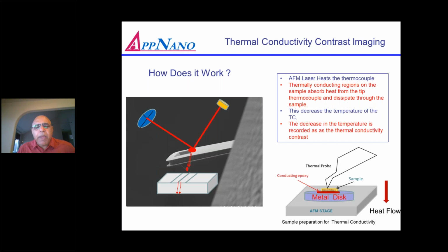The important part is to make a sample, and this is very, very critical. Sometimes if you have a polymer, you have a tendency to stick the polymer on a metal disc, and the metal disc is glued with a sticky tape on a stage. That's a very bad sample, because the idea is we want to have the heat transfer from the nanorod to the sample, to the disc, to the stage, and the stage is our drain basically. So you have to dissipate the heat. Avoid any insulation between the metal disc or any insulation between the sample.